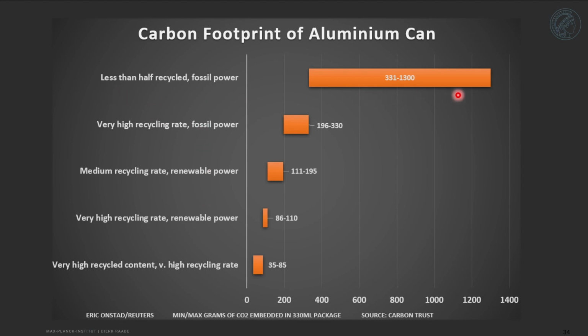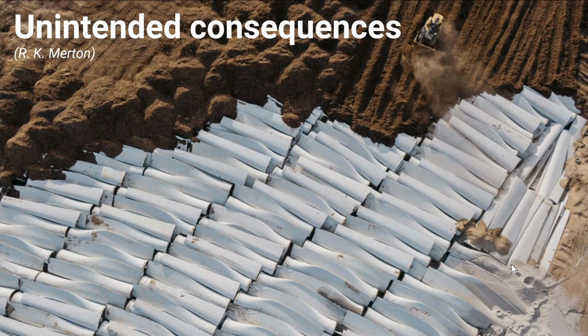Look at the upper bound, which actually does not look so good from the CO2 emissions. This is an example where the can was produced by only less than half recycled material that was being used in the melt and by the use of fossil power. The best case scenarios when you have a very high recycled content and likewise use a very high recycling rate after usage of the can. And you see this relationship, which goes down to about only 5% in the best of all worlds, relates roughly to the relationship between the aluminum oxide embodied energy when you produce the material mainly from the raw material, as opposed to the relatively low electrical energy that you need when you remelt the material from scraps, because aluminum has a relatively low melting point with only 660 degrees centigrade.